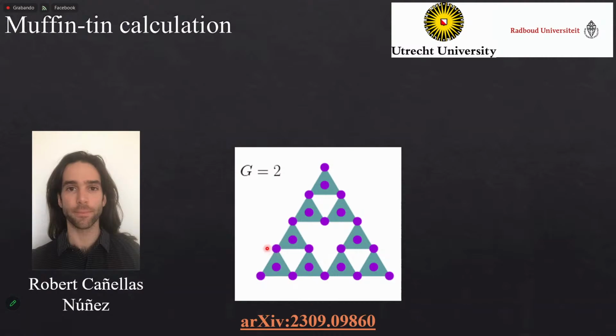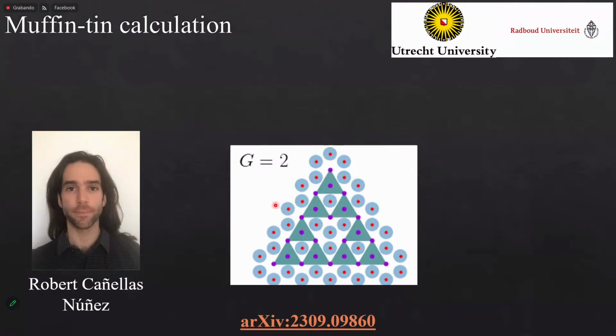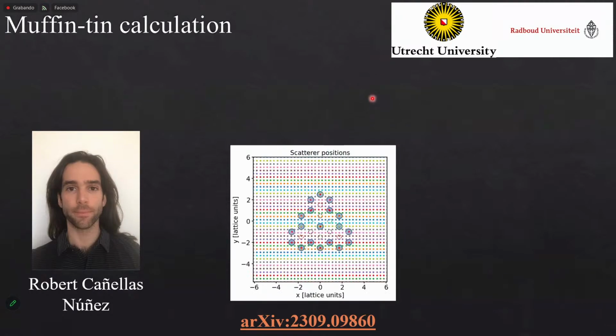To do that, we thought, okay, if I have an atomic potential, I would like the electrons to sit more or less in these regions. But we can think of an equivalent problem, using a repulsive potential so that the electrons will not like to sit in these holes of the system. This is how we modeled it: we have these potentials here, and we don't want the electrons to stay at these points. We start with a lattice like this, and then we put it on a grid. So we have this very simple idealization of how these flakes are, and we have a very big grid like this.